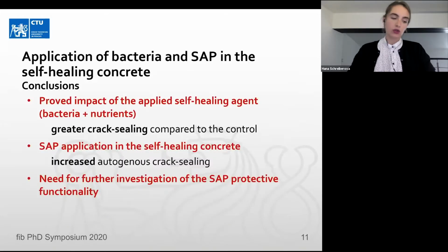So in conclusion, in this study, we detected several interesting points. Firstly, the proposed combination and dosage of the bacteria and nutrients proved to be suitable, as the crack sealing was enhanced by their addition compared to the control series. Further, the SAP itself seems to have a profound positive impact on the crack healing. In our case, it reached even better results than the bacteria addition alone. The combination of the bacteria and SAP in our study led to the most effective crack sealing.